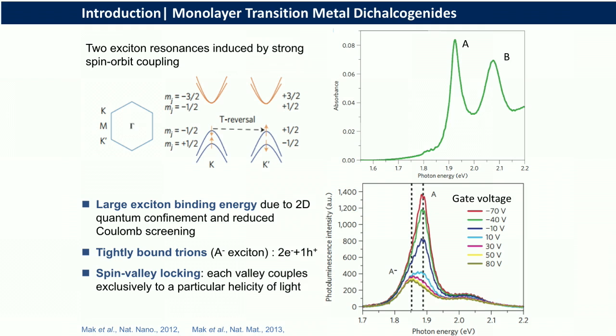So there's this beautiful work that came out many years back. I think this is from Tony Heinz's group, where they showed that if you take this material, then you get mostly emission from the free exciton. And as you start injecting electrons into the system via applying some gate voltage, then you can tune the emission spectrum, where the emission from the exciton decreases and the emission from what is called the trion, that's basically a hybrid of an exciton and an extra carrier, starts to dominate.